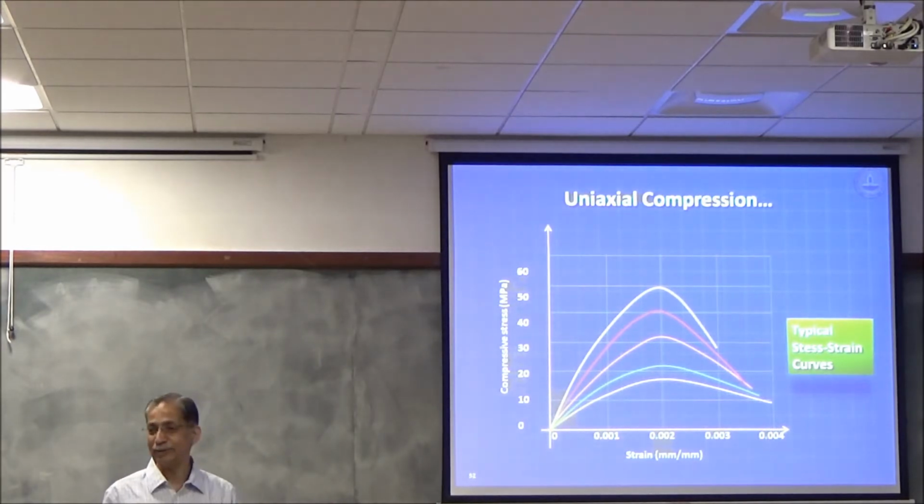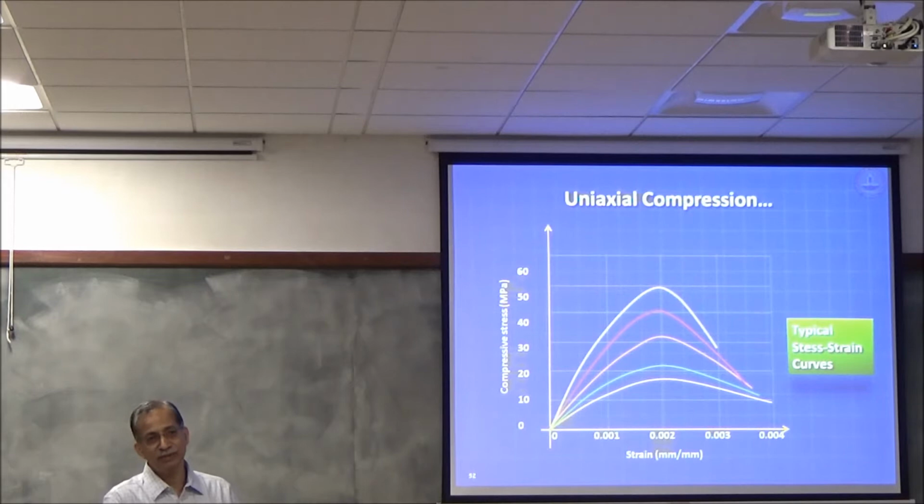So we'll hold that question, but you answer this. Now we'll go to this question. Why does it increase? Higher strength, you have higher elastic modulus. Why? In steel, it's not like that. Fe250, Fe415, Fe500, even pre-stressing steel, which can go up to 2000 MPa, more or less have the same elastic modulus, 2 into 10 raised to 5 megapascals.